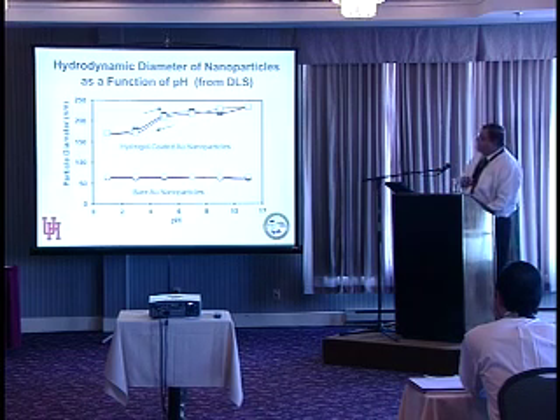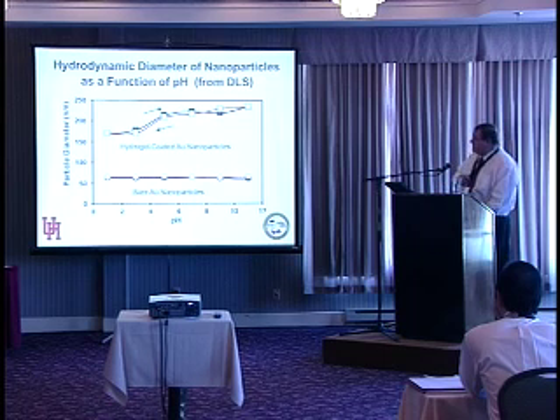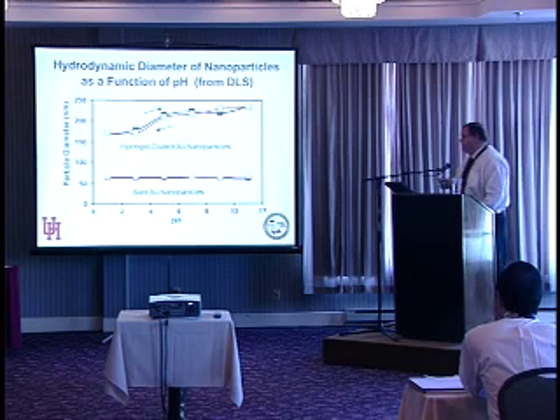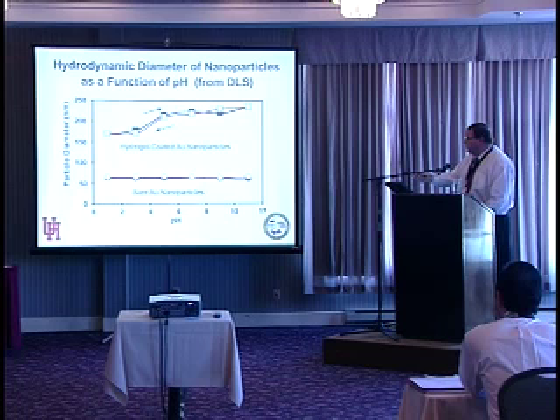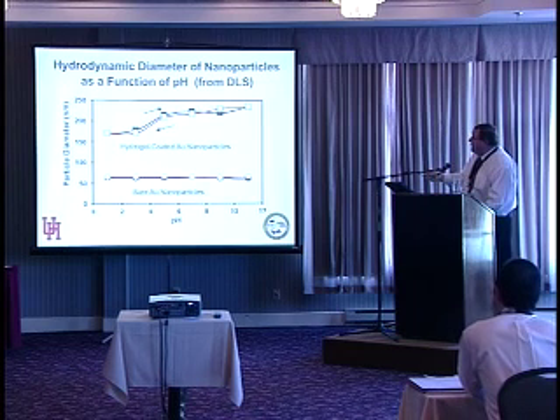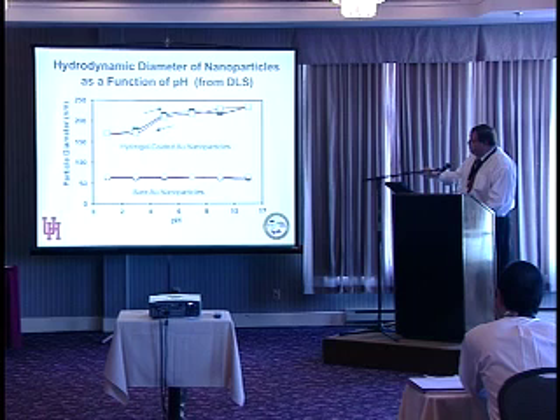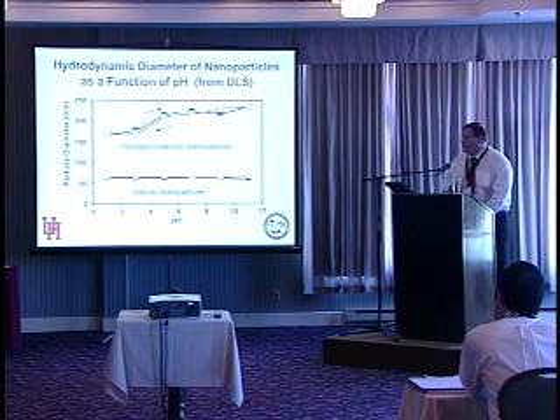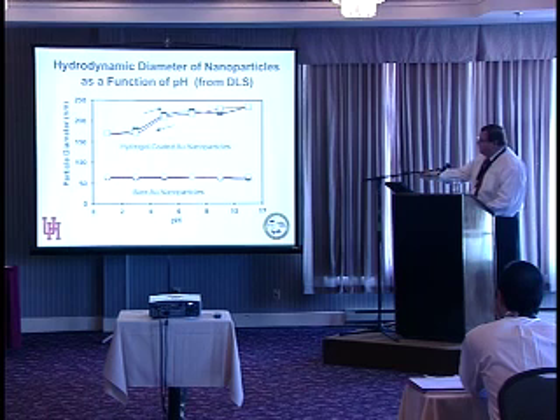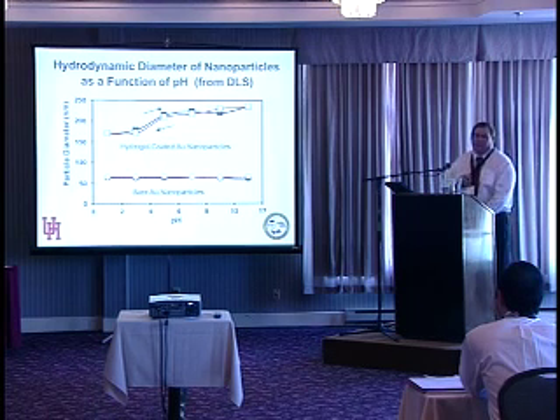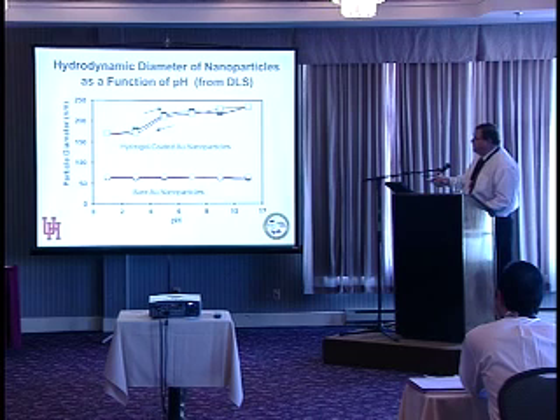Here are some hydrodynamic dynamic light scattering measurements of the diameter of our hydrogel particles compared to just bare gold nanoparticles as a function of pH. And so what you find is that at high pH, the nanoparticles are in their expanded state, the hydrogel is swollen. And then as you lower the pH, there is a point at which the diameter drops precipitously and collapses, giving your lower diameter here. In comparison, the bare gold nanoparticles show no variance with pH in terms of their diameter.